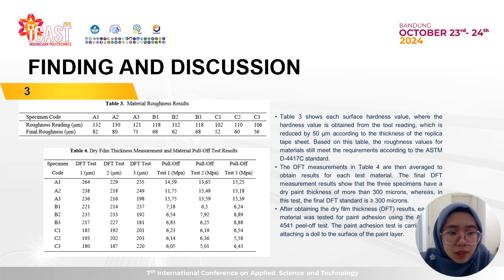There is a specimen result about roughness reading and final roughness, and it still meets the requirement according to the standard. And the DFT measurement, we can look in Table 4. It's about the dry film thickness measurement, or DFT test, for each code A, B, and C.